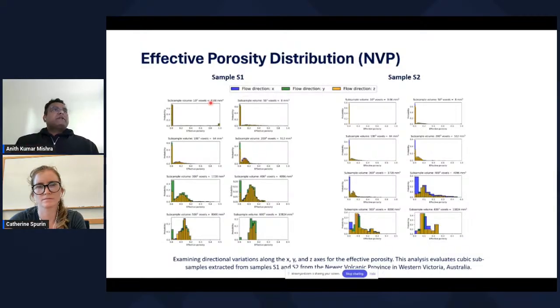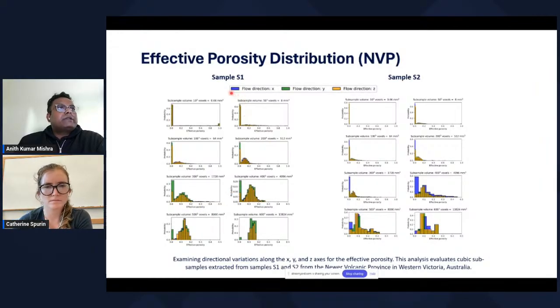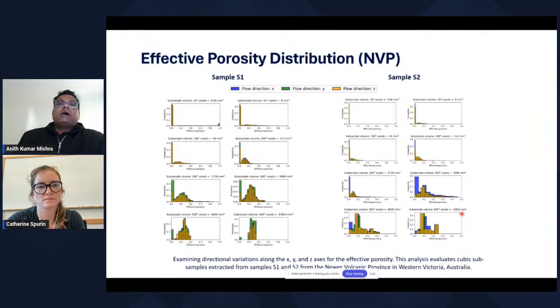Coming to the REV-based effective porosity distribution for the Newer Volcanic Province sample. We started with a very small cuboid subsample with 10 to the power 3 voxels, and we see that we are not getting any convergence. But as we kept increasing the voxel sizes, the effective porosity along the three different directions X, Y, and Z starts to converge. Although the convergence is not very good, in that we are not able to see a single histogram bar, this is what we could get from the sample size that we had. The same pattern was observed for the other sample as well. So we can say that the effective porosity started to converge at a volume of 600 cubic voxels, which corresponds to 13,824 cubic millimeters. This is the sample size in terms of volume that we need to establish the REV for basalt.